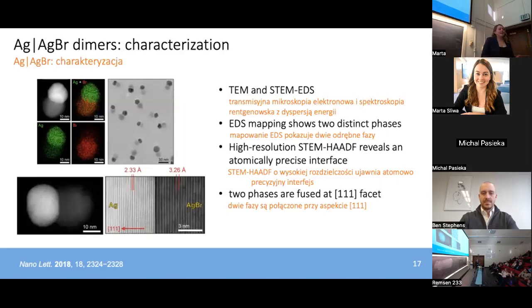So EDS mapping here showed that the dimer products are made of two distinct phases. Here we see the silver corresponding to the green in that silver phase, and the red color corresponding to the bromide in the silver bromide phase of those dimers. The phases are also joined by an atomically precise interface, as we see in the STEM data here. And they're fused by what we've identified to be the 111 facet, which is a key feature of the system that's going to come up a few more times in my talk today.